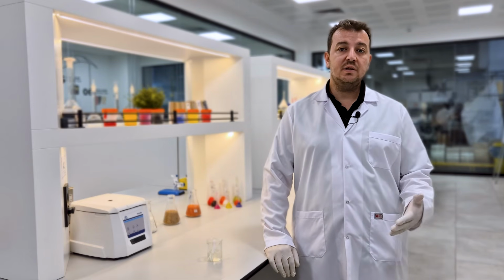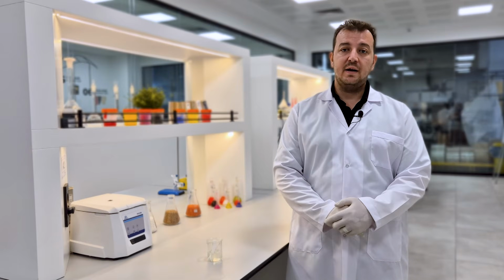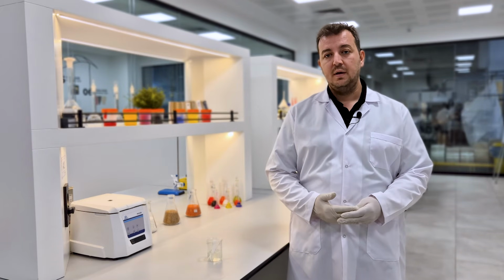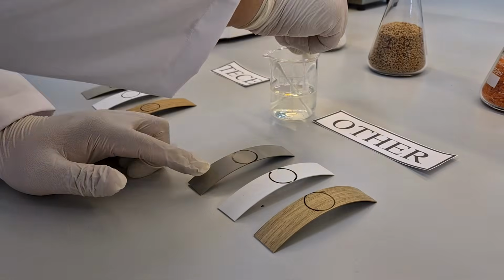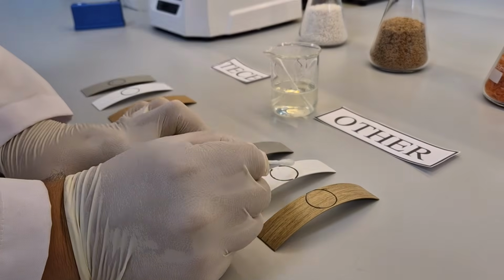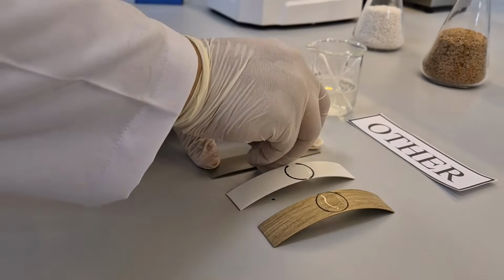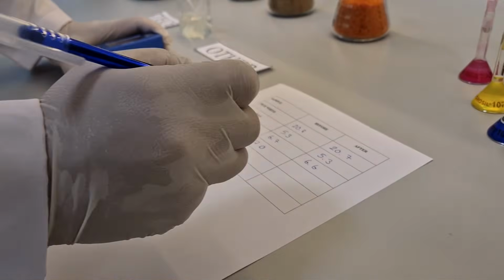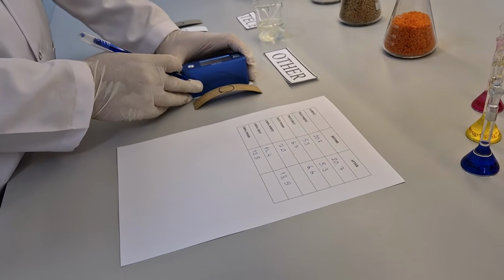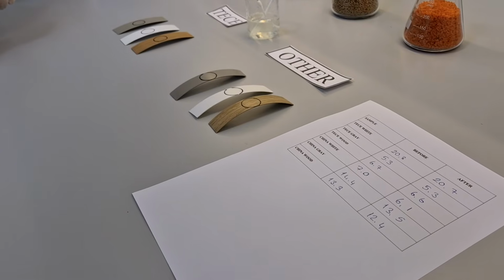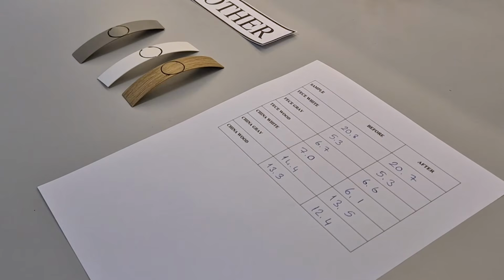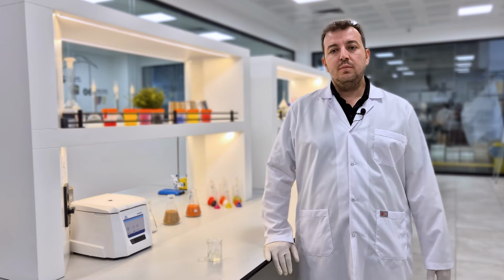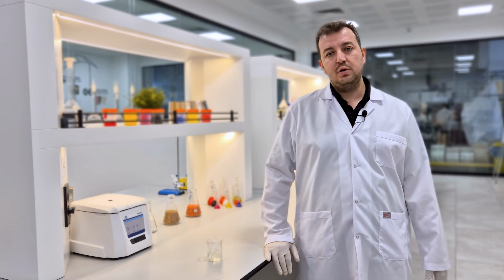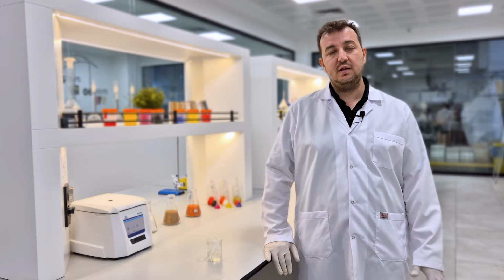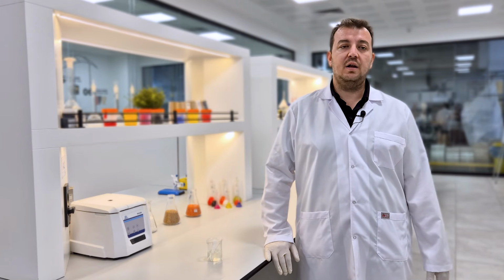Another important test for home users is the resistance to cleaning chemicals. The chemicals used during cleaning can cause color bleeding and dullness on weak surfaces. In gloss meter measurements taken before and after the test, it can be clearly seen that dullness formed on the surface after the chemicals were applied. In this test, we applied bleach to the surfaces and examined the effects. On the other cheap edge banding, significant dullness and paint fading were observed after bleach application. On the Tech product, however, there was no change to the surface. This is very important for home users. In quality production, surface protectors prevent cleaning chemicals from causing damage, while in low-quality products, such damage is inevitable.